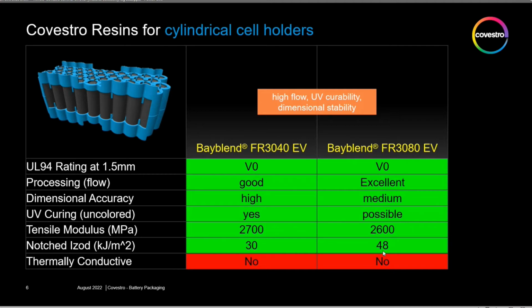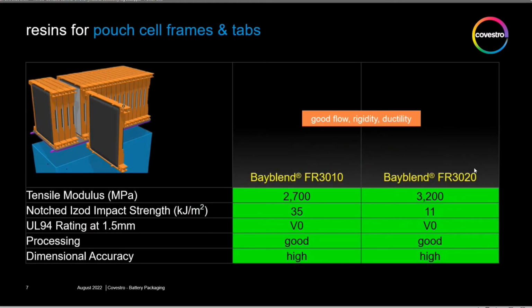And a secondary product, just based on whatever the requirements are, is Bayblend FR3080 EV. So as you can see here, this has a higher notched Izod value, indicating it's a better impact material. So if impact is something that's very important, we go with this material. If it's not as important, we stick with 3040 EV.